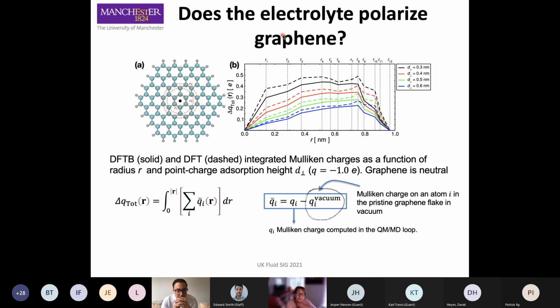With this procedure, we can actually see the proper polarization of the graphene. For example, let's say I have this flake of graphene and an ion at a different distance from the surface. I see the surface from the top in this case, and the ion is at different distances from the surface. Here what we plot is the total charge of the carbon in the first ring, in the second ring, in the third ring, etc.